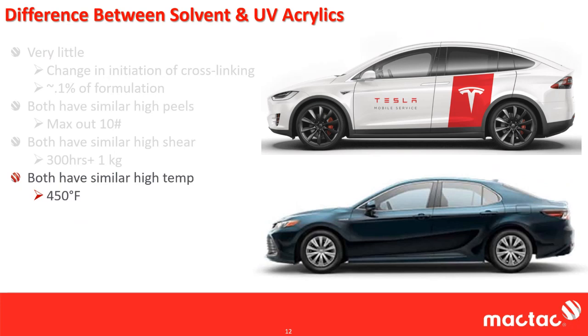They're both going to have similar high temperature range, which is about 450 for acrylics. Getting much higher than that, you have to go into the silicone-based adhesives, but there are UV options and there are solvent options that are going to get you up to that high-end temperature range of about 450. Both have similar LSE. Now, acrylics as a whole do not have good LSEs. I won't say that they make great LSE adhesives. They're nowhere near as good as rubber, but acrylics can be modified with tackifiers to have LSE properties. This can be done with both solvent adhesives and it can be done with UV acrylics as well.